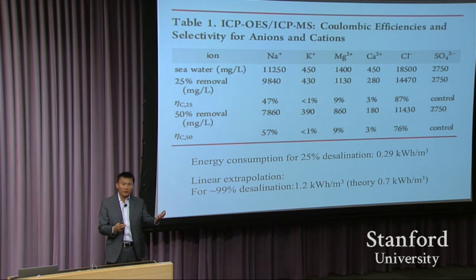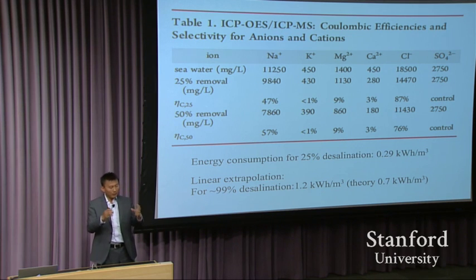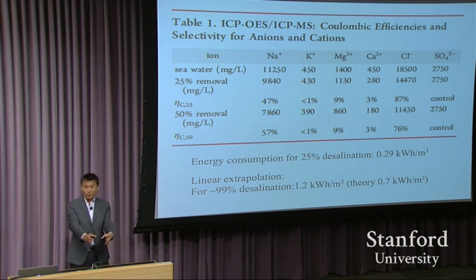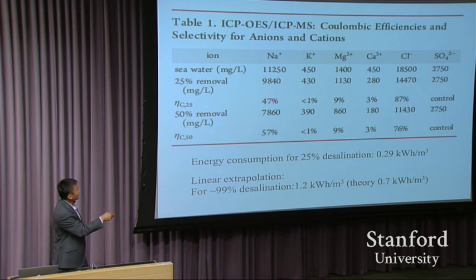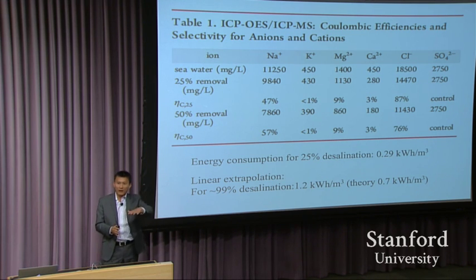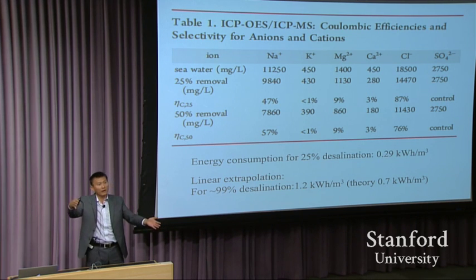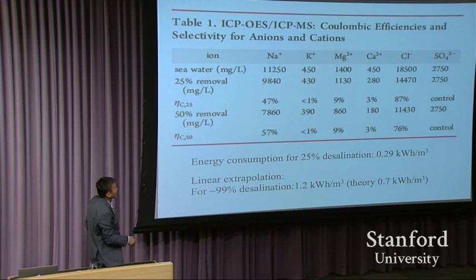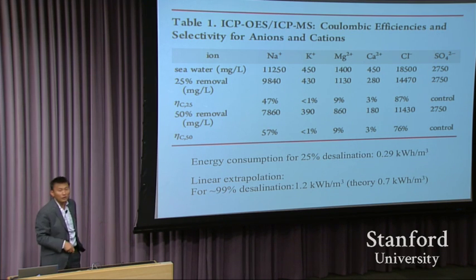I know how much current I put in and the time, electrical current. I can calculate the charges I put in, how many electrons I put in. And after I do this desalination, I can measure the concentration still remaining in the water, right? Now 47% of the electricity takes out sodium ion, and about less than 1% is potassium. We can also take out a little bit of magnesium and a little bit of calcium. You see chlorine on the anion side, this is 87%. Cation, positive charge, is 100%. Anion, that's negative charge, has its own 100%. Here is mainly chlorine.